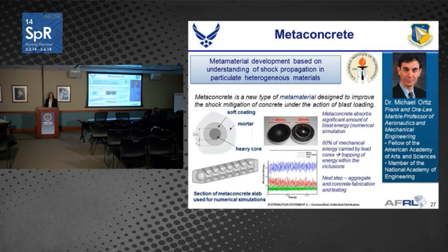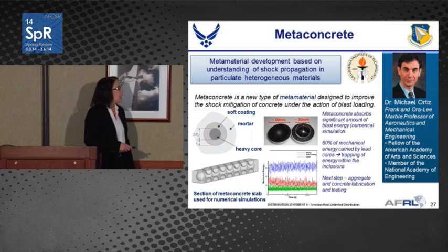One of the ways that they're using this idea of being able to mitigate the blast wave in the composite materials through the Center of Excellence is this idea of what they call a meta-concrete. In this material, they take a heavy core, in this case lead, and surround it with a soft polymer coating, and they embed that in a traditional concrete mortar.